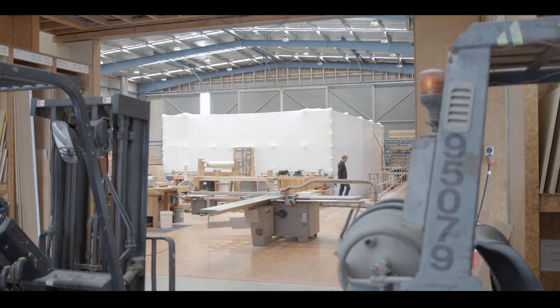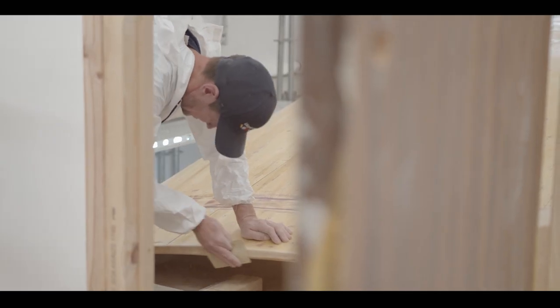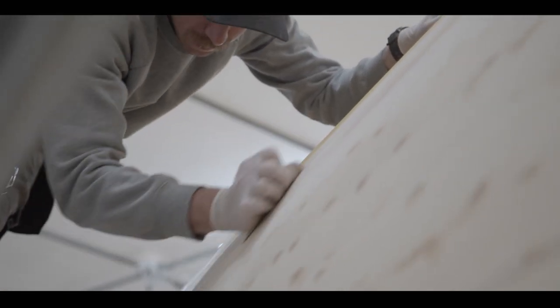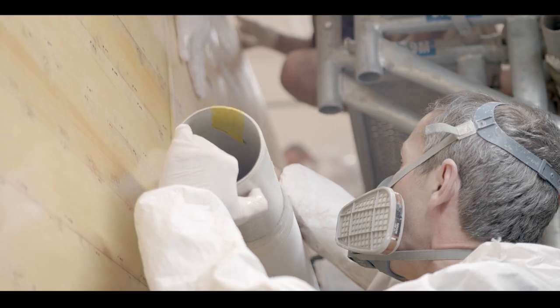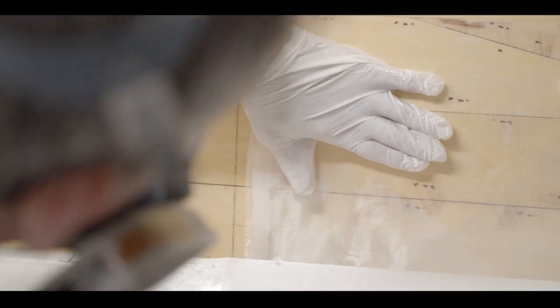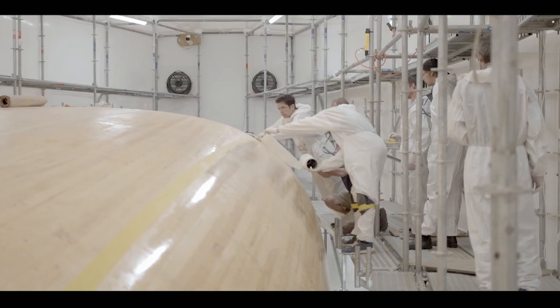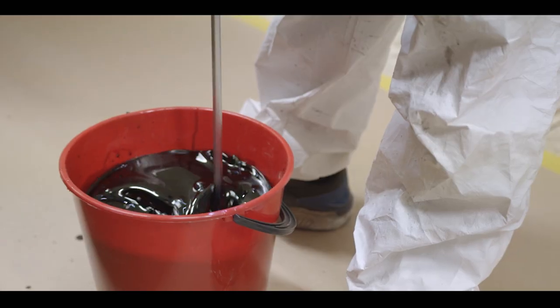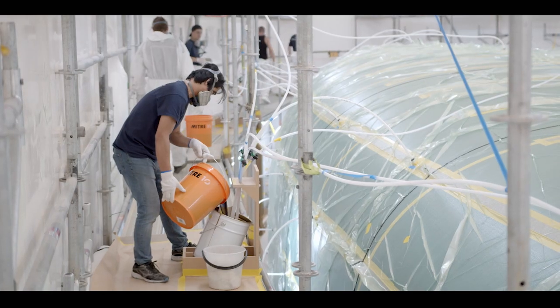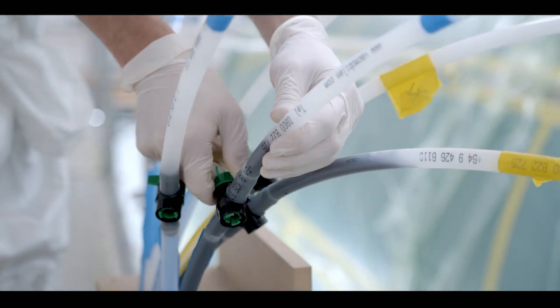With the timber planking completed, the hull was then covered in a tent, and preparations for applying the composite outer skin began. A highly developed eye for detail was needed to smooth out the timber's natural imperfections. Then the layers of Kevlar and e-glass cloth were carefully applied. Vacuum infused to ensure the Kevlar and e-glass was properly bonded to the cedar hull, an important consideration as she'll be exploring high latitudes and remote places.